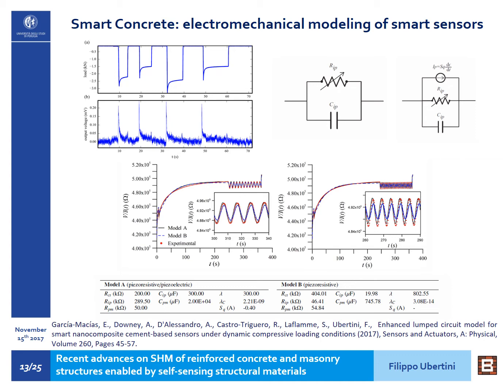On the right you see a more advanced model where we also add a third branch to the circuit, and that branch reproduces the piezoelectric behavior of the sensor that we have shown is present in these materials. So essentially, when the material is loaded, a little bit of voltage develops in the material itself. So the material is not only piezoresistive, but it also has some piezoelectric behavior, and this is introduced in the third branch of the model.